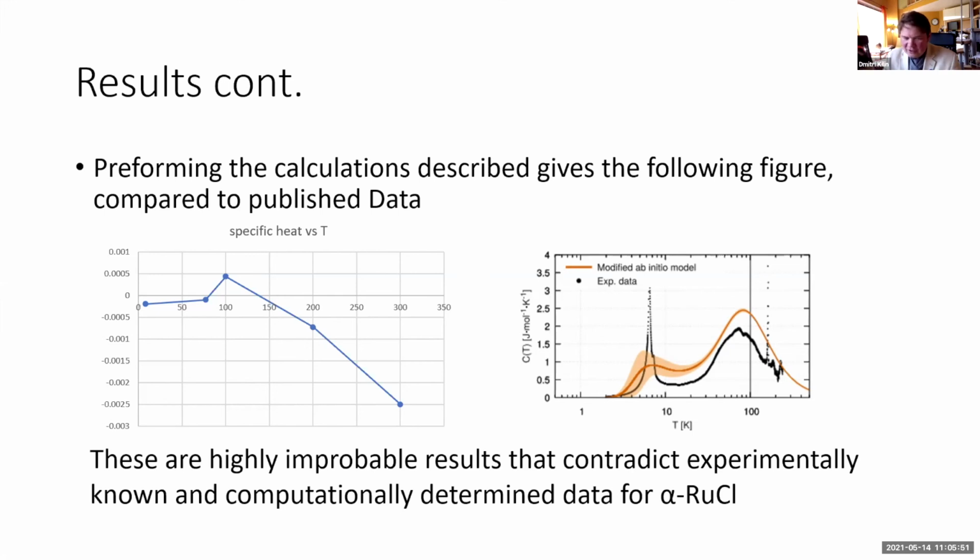Does it have any relation to the second peak? It could. Unfortunately, I was not able to get the program for making a video out of the molecular dynamics calculations to work, so I wasn't really able to look at that. But you can hypothesize that likely the second peak originates from activating some interatomic vibrations. So it would fit the Einstein or Debye models for heat capacity. Yes. So it's not magnetic in nature, it's just oscillations in solids.